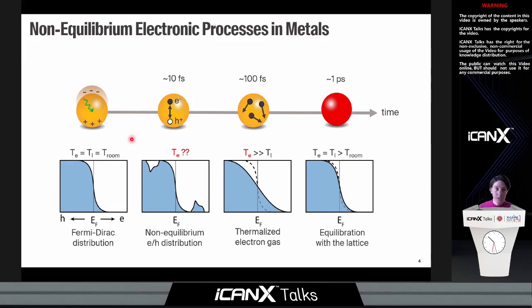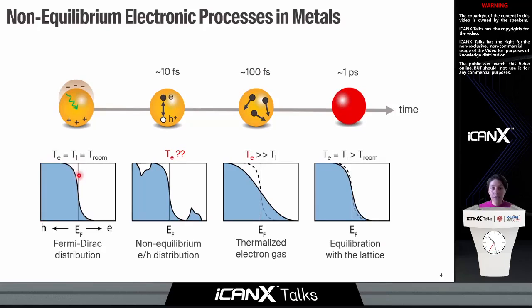If we have a look at the energy distribution of these electrons and holes in the band structure, things become quite interesting. What you're seeing in these bottom graphs is the Fermi-Dirac distribution of the electron population in the metal. Obviously, when we start, this Fermi-Dirac distribution has a temperature that is equal to the lattice temperature and the temperature of the environment. However, upon prompt generation of these hot electrons and holes, we would observe a population of electrons and holes which have a very strange distribution, which cannot be described with a specific temperature for the Fermi-Dirac distribution. At the same time, on a longer time scale, the electron gas will collide and thermalize, but this time it will reach temperatures which can be extremely high.